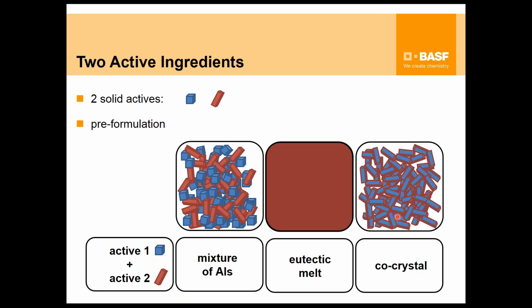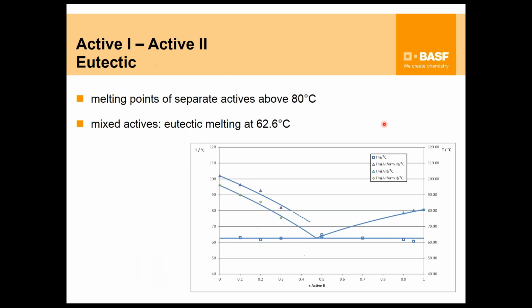And I also can have a eutectic melt. So what is a eutectic melt? Actually, it's somehow similar to the co-crystal. In the co-crystal, the 2 actives like each other so much that they form a new crystalline form. In the eutectic melt, they also like each other, but they don't make a co-crystal. They melt and interact in the melt. And this is what we observed for one system, and that's what I want to show you.